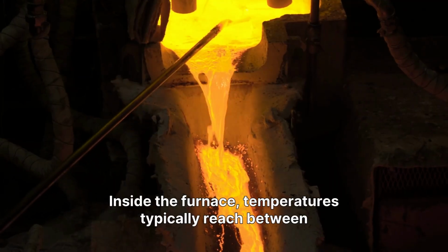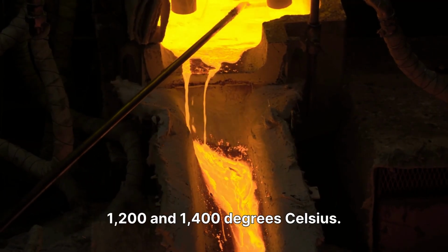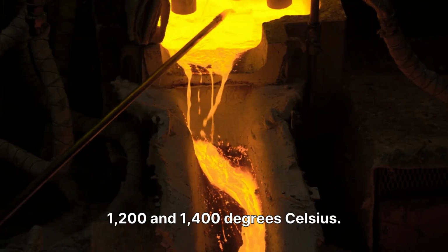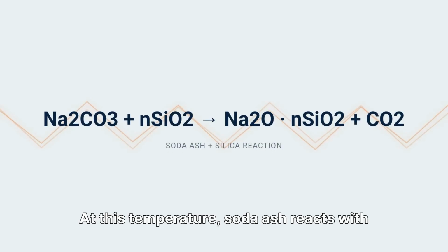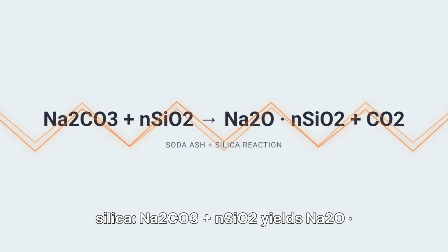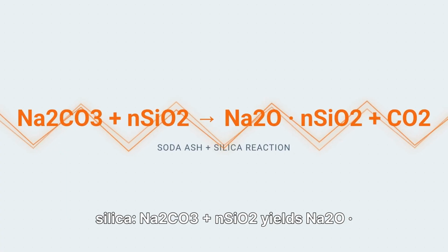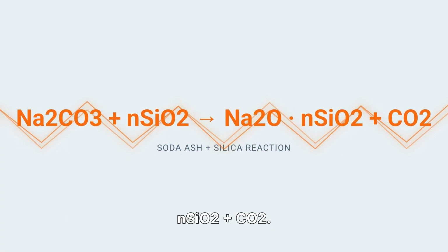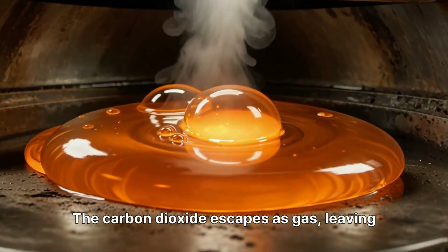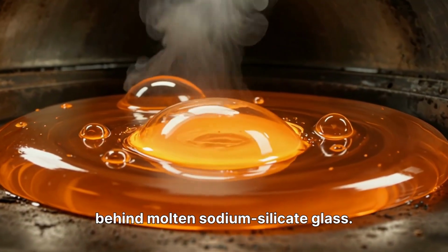This dry batch is continuously fed into a gas-fired, oil-fired, or electrically heated melting furnace. Inside the furnace, temperatures typically reach between 1,200 and 1,400 degrees Celsius. At this temperature, soda ash reacts with silica: Na2CO3 plus NSiO2 yields Na2O.NSiO2 plus CO2. The carbon dioxide escapes as gas, leaving behind molten sodium silicate glass.